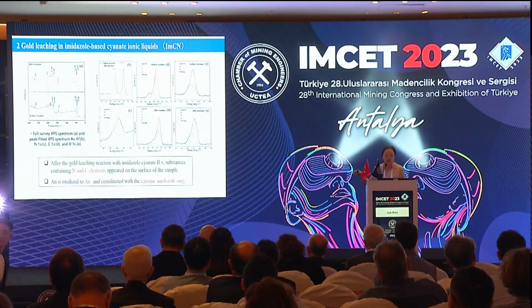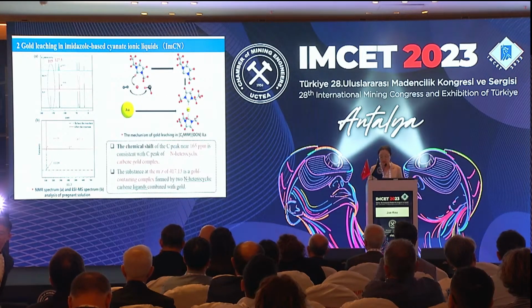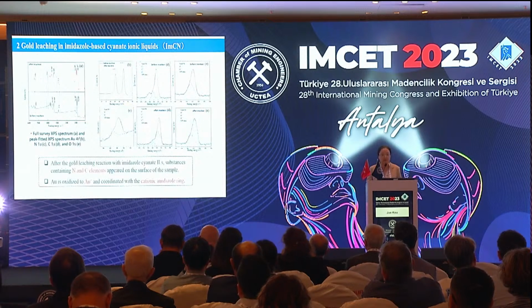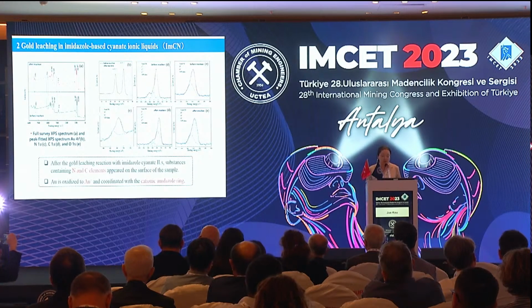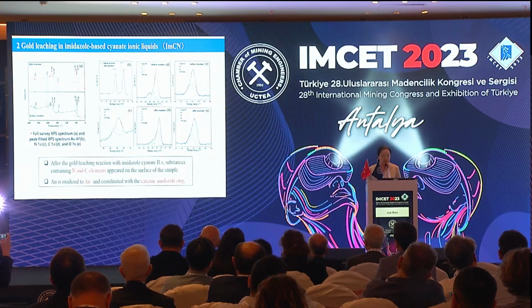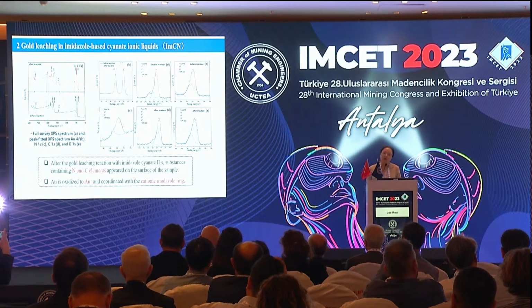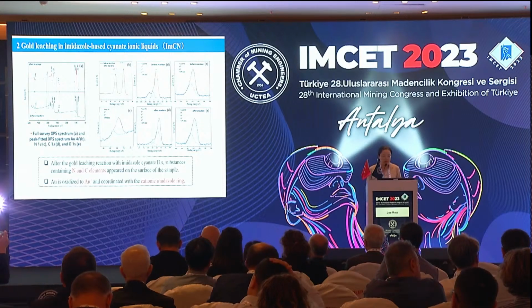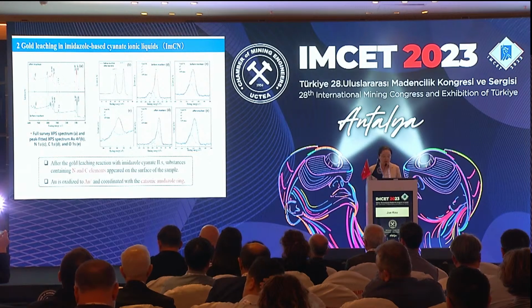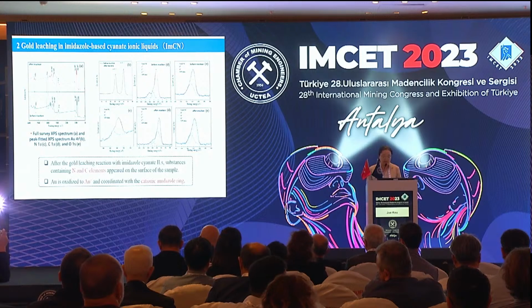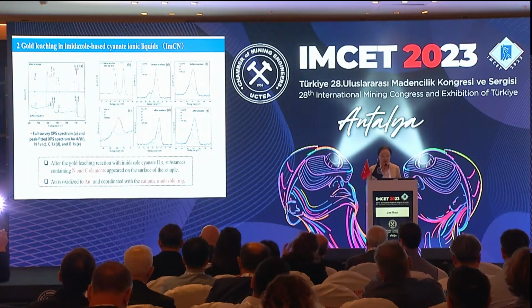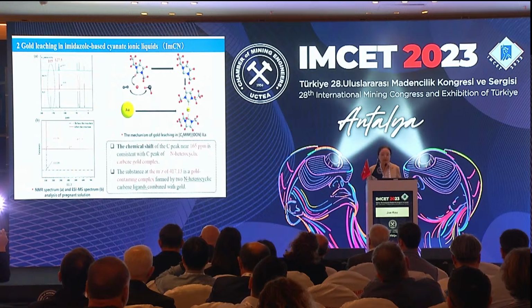And we can see that before the leaching, the surface is quite smooth, but after leaching, it became rougher, and the gold coating is all dissolved in the liquid. And this is the XPS spectrum of the leaching residue. And here we can see that the gold is oxidized to gold plus and coordinated with the cationic imidazole ring. And also we found nitrogen and carbon on the surface of the residue.